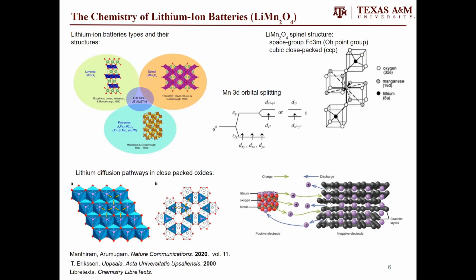This causes the manganese to be reduced, and as this reduction occurs, a Jahn-Teller distortion occurs and the manganese 3d orbital splits. This causes the symmetry of the crystal structure to decrease from cubic to tetragonal. The graph in the middle shows this Jahn-Teller orbital splitting, and an energy release of magnitude epsilon can be seen. This energy is what powers the cell and makes the battery work.